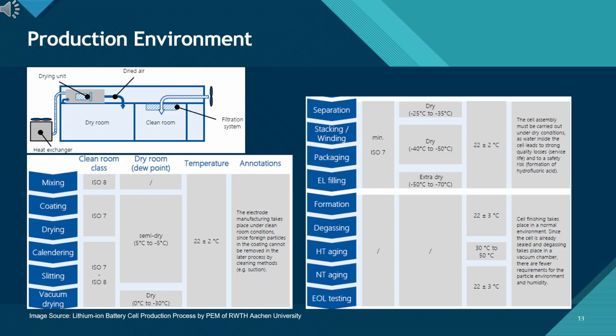Here, ISO 7 and ISO 8 refer to international clean room classes. ISO 7 permits up to 352,000 particles per cubic meter, greater than or equal to 0.5 µm, while ISO 8 permits up to 3.5 million. These classifications ensure that foreign particles do not become embedded in electrode coatings, as such particles cannot be removed later and are a major cause of internal short circuits.